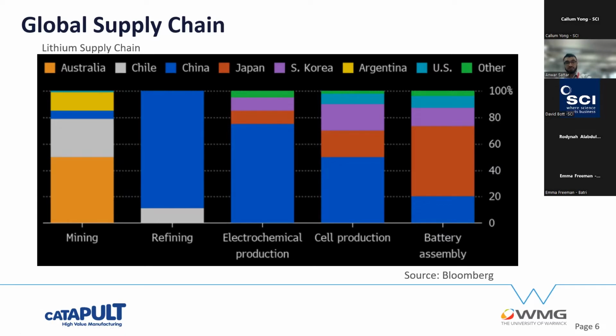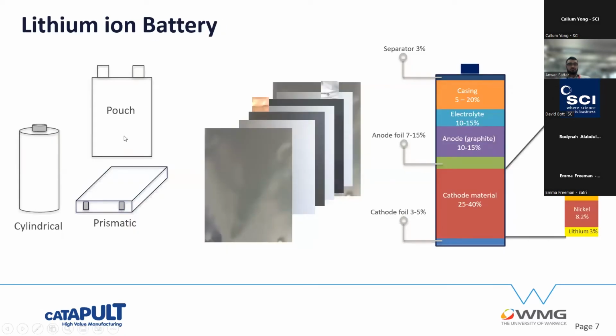A lithium-ion battery can come in many shapes and forms. You've got cylindrical cells, pouch cells, prismatic cells, but once you look underneath, they're almost all the same. You've got an anode, which is graphite and copper, and you've got a cathode, which is aluminium with a coating, which is a lithium transition metal oxide. And then you've got separators in the middle. The way it works is lithium travels from the anode to the cathode and vice versa when you're charging and discharging. And this chart here shows the material composition of a lithium-ion cell.